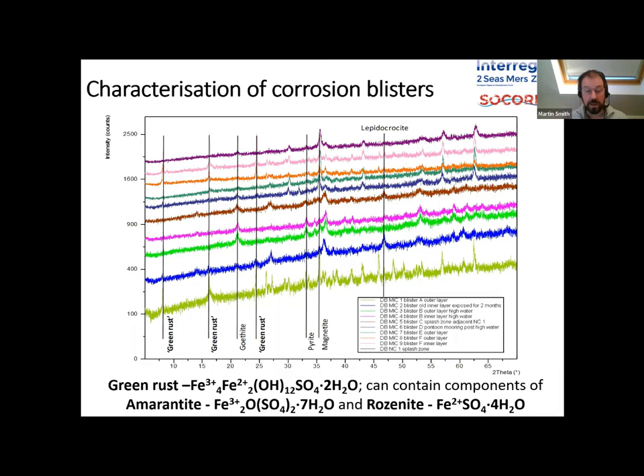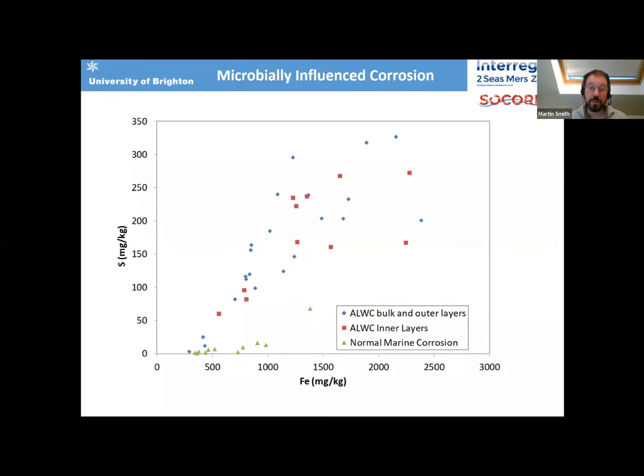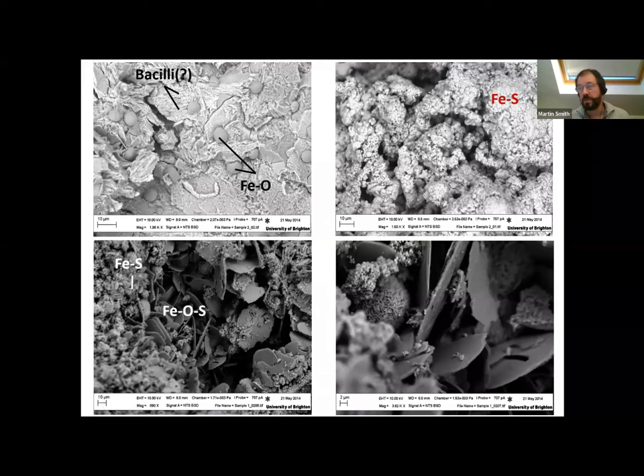So a really diagnostic part of some of these corrosion blisters is the occurrence of iron sulfates in with the oxide corrosion products. And if we just go in and chemically analyze some of those corrosion blisters, we get a strong differential between these bright orange rapid corrosion blisters and what we'd call normal corrosion in the amount of sulfur that's present. So the sulfur metabolism and the sulfur mineralogy is really important in terms of what is going on in these structures. These are just some SEM images of what some of this material looks like.